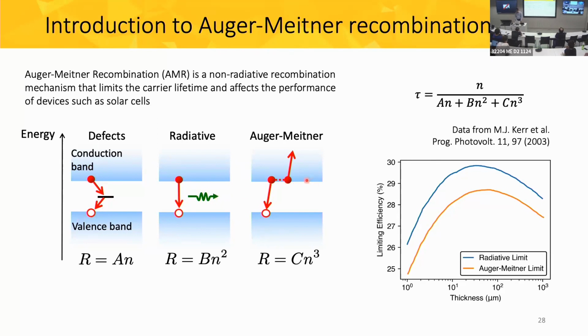However, if you have an extra electron or an extra hole, there's one more channel where the energy can be lost, where the electron recombines with the hole and the energy gets transferred to that extra electron, gets kicked up to a higher state, and eventually the energy is lost back to heat. This process is important in LEDs, it's important in lasers, and something that I also found out along the way, it is also very important in silicon solar cells.